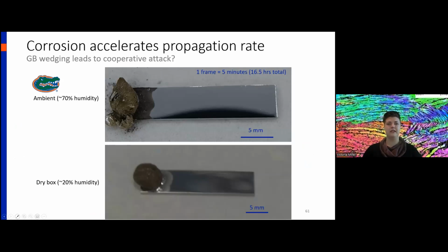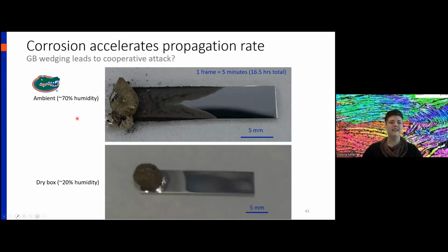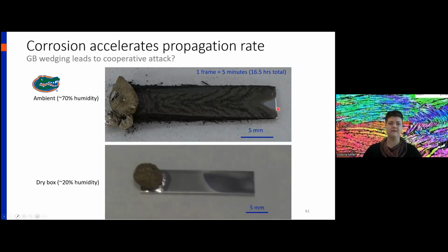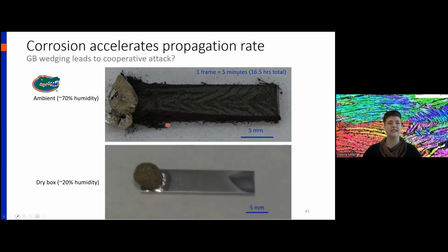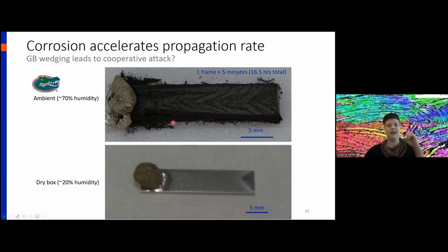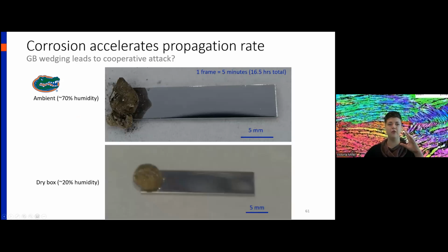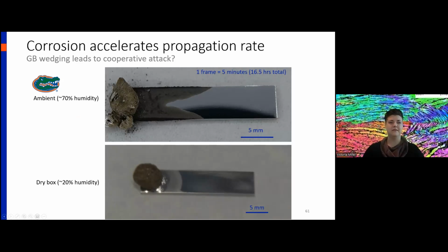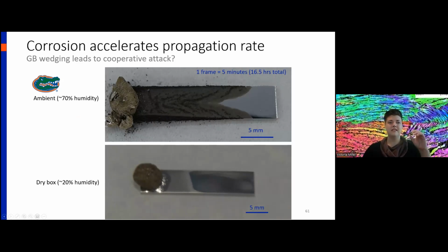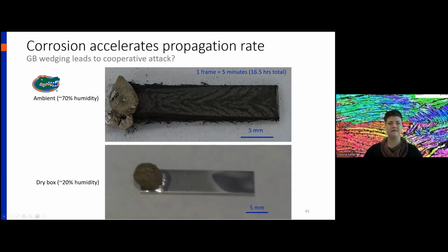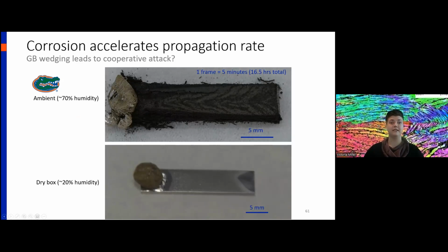The other thing to note here is that corrosion accelerates the propagation rate. And our hypothesis here is that you're getting grain boundary wedging that leads to cooperative attack. So as the formation of the corrosion product wedges your grain boundary open, that allows the liquid metal to flow in more easily. But that's still the subject of ongoing study.